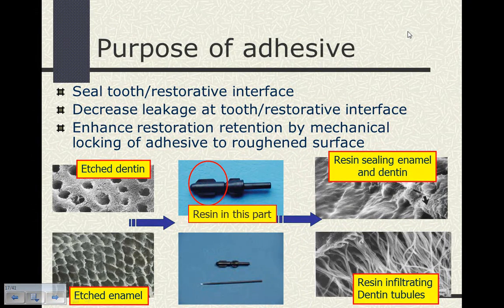The purpose of the bonding system is to seal the tooth in the restorative interface. It decreases the leakage at the tooth restorative interface. It enhances restoration retention by mechanical locking of the adhesive to the roughened surface. In fact, if we look at the images on our left-hand side, you can see what etched dentin looks like, where the tubules are opened up, and the peritubular dentin looks like a sponge. The enamel surface on the lower left looks like carpeting. We then apply the resin adhesive to the dentin and the enamel, and when we light cure this adhesive, it seals the enamel and dentin interface. The resin infiltrates the dentinal tubules, and we create a hybrid zone within the peritubular dentin.